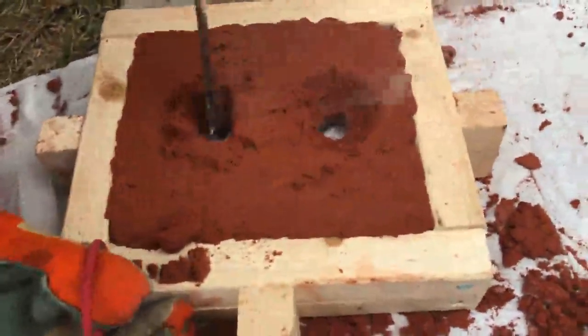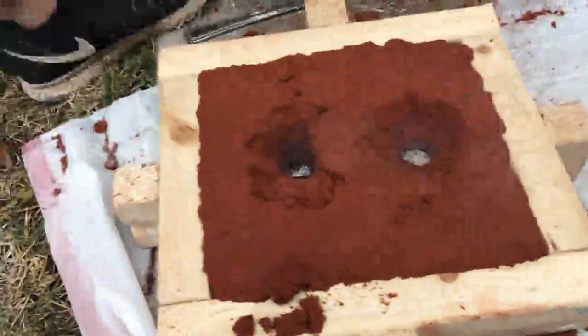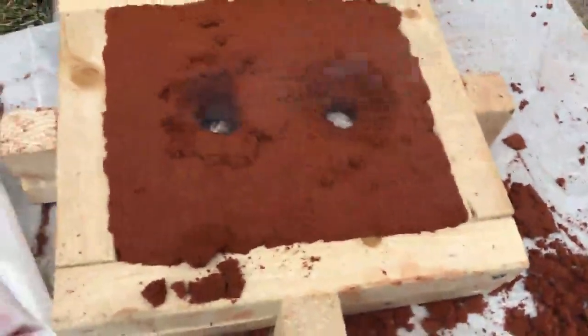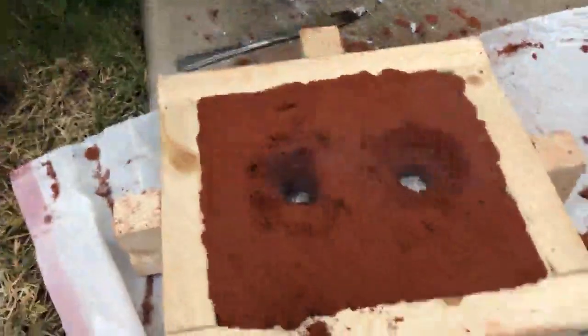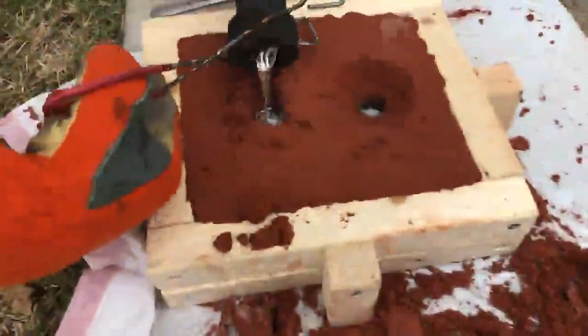We realized after it was fully poured that the sprue and the riser had not fully filled. All remaining aluminum was heated and melted down and then poured into the mold. Once all aluminum was fully poured, we then had to wait approximately 20 minutes for it to cool. As expected, the aluminum shrank throughout the cooling process.